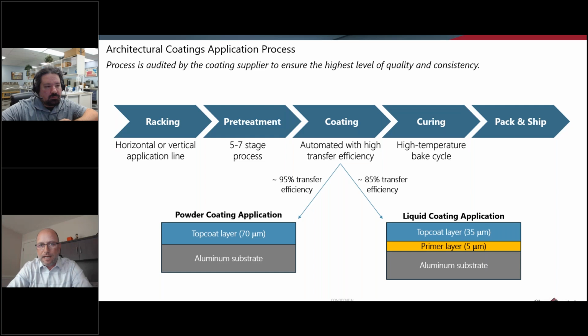Even the liquid coatings are applied, the highest efficiency ones, using an electrostatic bell sprayer. And those have pretty high application transfer efficiency. So what I'm saying here is about 85% on average of that material is going to hit the part and be usable. 15% will go past the part and is wasted.